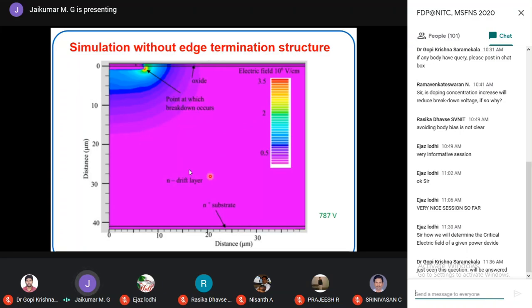This is basically the electric field contour of the device. You can see that the maximum electric field is 3.5 × 10^6 V/cm, around 3 megavolts. Obviously the material is not silicon, that is why it is 3.5 megavolts. For silicon, the critical electric field of breakdown will be how much? For silicon, it will be around 300 kilovolts only. This is 10 times higher than that. It is because the material is not silicon, it is silicon carbide. So a simulation without any edge termination structure can yield 787 volts.